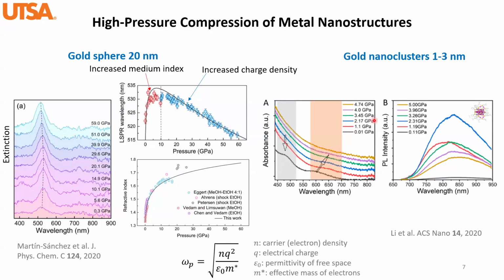Well, in our experiments, we're trying to look into this, using high pressure compression and trying to modify the electron-phonon coupling. But of course, if you're talking about superconductivity, that's why we're thinking about, probably, also talking to Ross and Steve about the hydrides. So we can take a look at whether there's any chance that we use superconductors to carry surface plasmons. In this case, we're not expecting significant losses introduced by electron-phonon coupling, right?